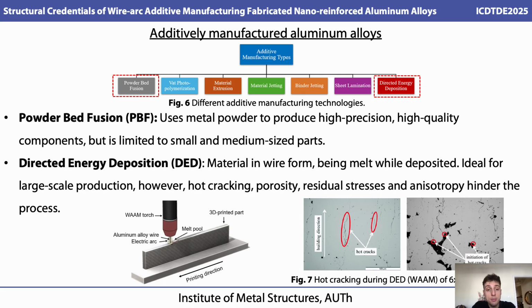In directed energy deposition, also known as DED, the material is in wire form, it is being melted while deposited, and the method is ideal for large-scale production. However, disadvantages are also here. As you know, we have hot cracking, porosity, residual stresses, and anisotropy, which hinder the adoption of the process. In figure 7, you can see the hot cracking that occurs while printing 6 and 7 series aluminum alloys.